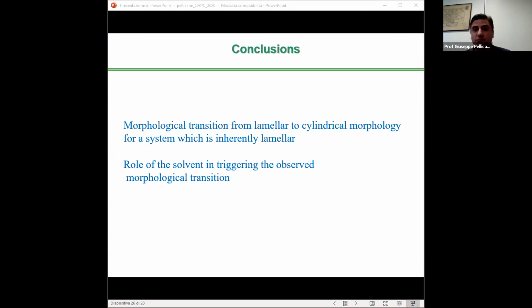In particular, in the present work, systematically changing the interaction strength between one block of the polymers and the solvent, while keeping the remaining interaction parameters constant, resulted in a morphological transition from a lamellar to a cylindrical morphology for a system that is inherently lamellar in the absence of solvent. These morphological transitions are directly linked to the unbalanced distribution of solvent beads throughout the film, causing one block to behave like a minority phase and form a cylindrical morphology.